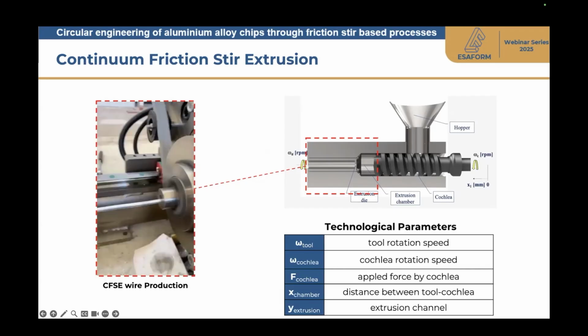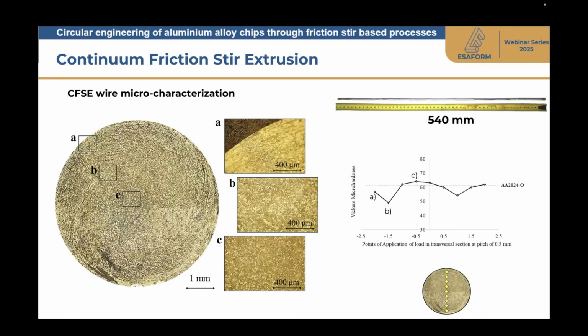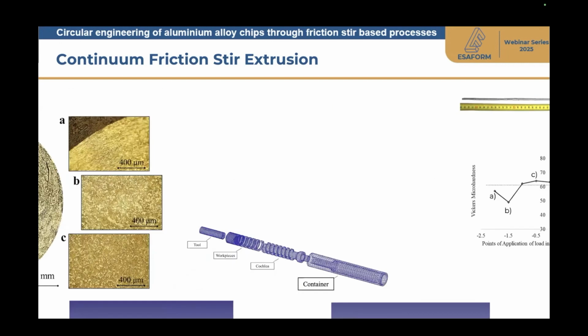It should be observed here, you see the result of one of the experiments, so half a meter, but we obtained even a couple of meters or something like that. But the problem there is to properly maintain the process stable, first of all, with the proper stable addition of new chips. And again, here you see the transverse section of the wire with the considerations we already carried out for the friction stir extrusion process with several aspects.